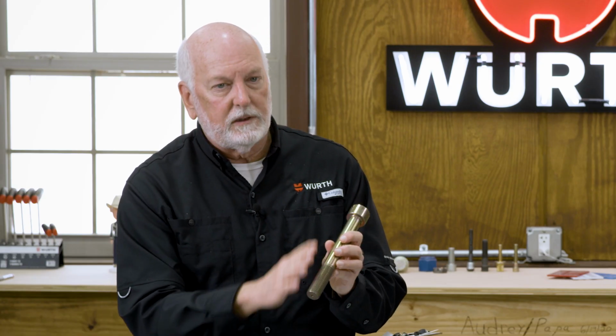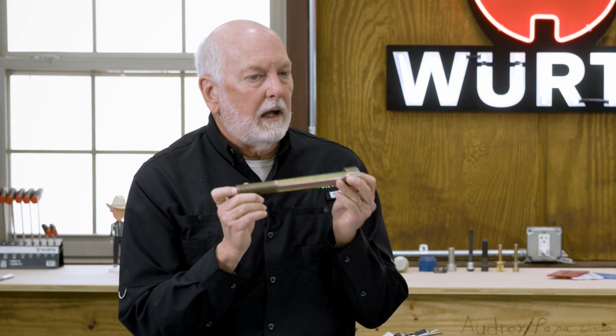And we know for a fact that product is out there in commerce that has inclusions, it has hard banding, and these are opportunities for hydrogen atoms to be trapped in there and cause this problem. So in laboratory testing, where they do full micro-examination, they have good, clean, pristine steel. Right. Yes, I agree with the lab test that upwards to HRC 39, that material's not susceptible, but that's not the real world. So we have taken a stance on this. So we are not in agreement with some of the specifications. Example, ASTM F1941 specifically says that you don't really have to bake. True. And we say we do.